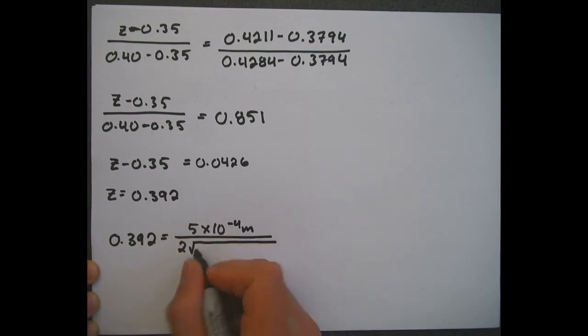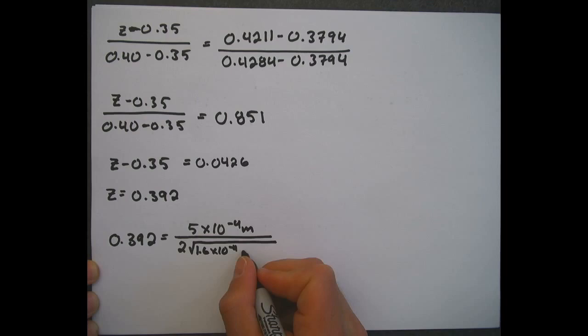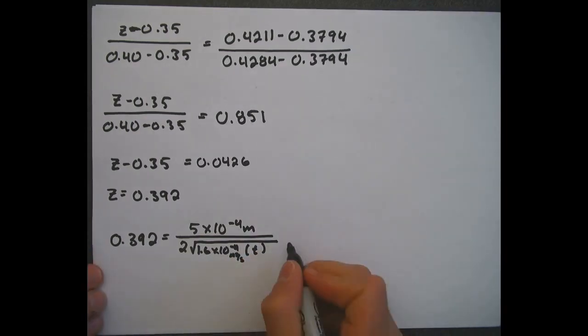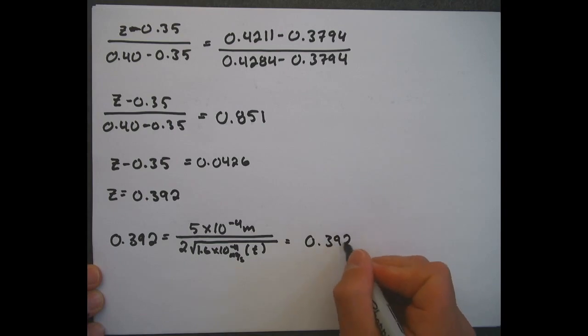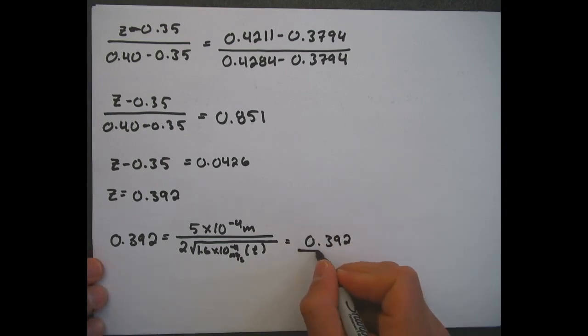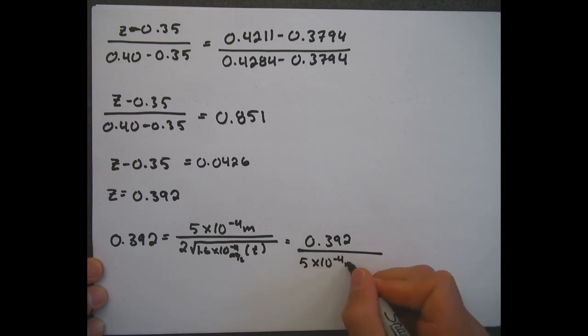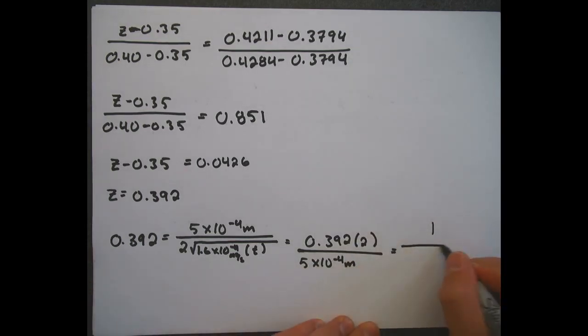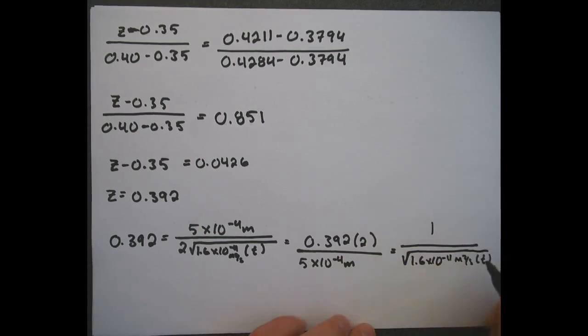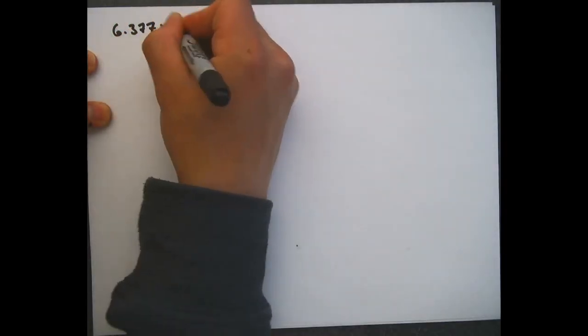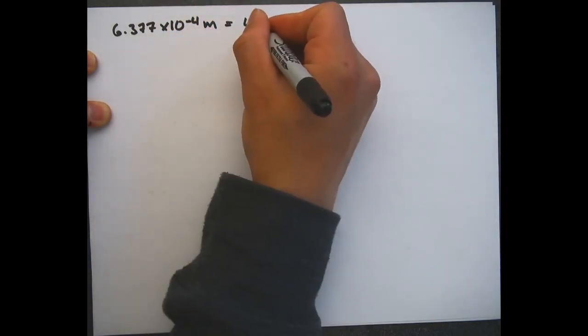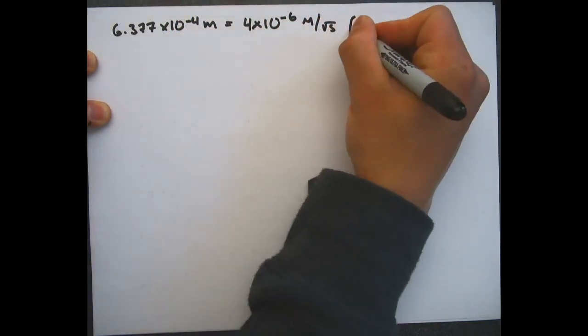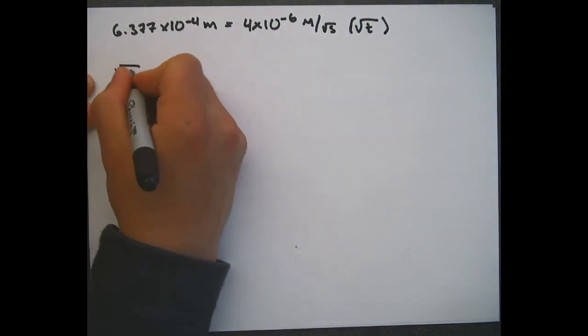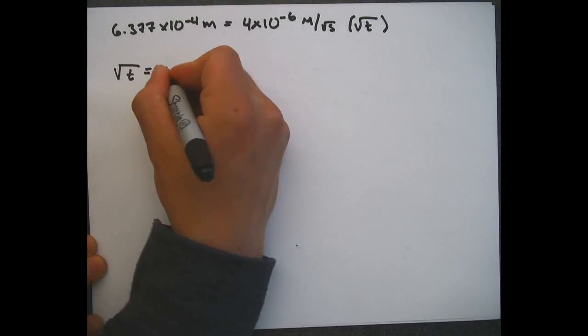Now, because z equals x over 2 times the square root of Dt, I told you this would come in handy, we can set them equal to each other and solve for our time t. We get rid of the x on the other side and the 2 in the denominator, and we set that equal to 1 over the square root of Dt, where D is 1.6 times 10 to the negative 11th meters squared per second, times time. Solving the left hand side, we get 6.377 times 10 to the negative 4th meters, and we set that equal to 4 times 10 to the negative 6th meters per square root of seconds times the square root of t.